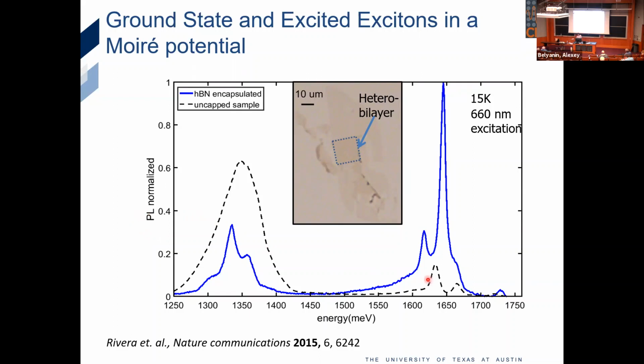When you stack them together, you do get these interlayer excitons that appear at lower energy, mainly based on the band alignment. But at the beginning, everybody was making Moiré vertical structures with probably pretty poor quality, meaning there were a lot of variations of local strains and defects. So starting a few years ago, people started to encapsulate them with atomically flat hBN insulator. It really played a major role in improving the quality of the Moiré superlattice. It's just more painful for students to create.